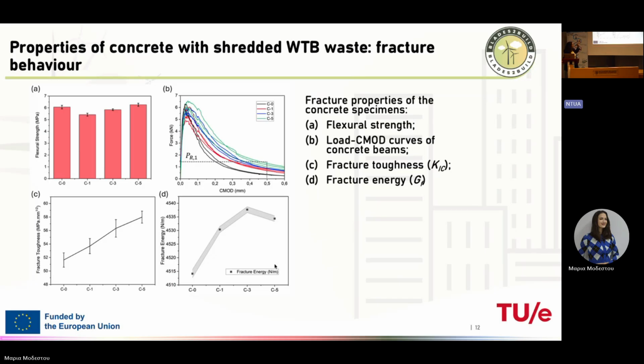flexural strength. This is figure A. So we can see that at higher dosage, the flexural strength tendency repeats the splitting tensile strength. We have really nice results and an insignificant reduction at the lower percentage of waste. And at 5%, we have the same as compared to the control.